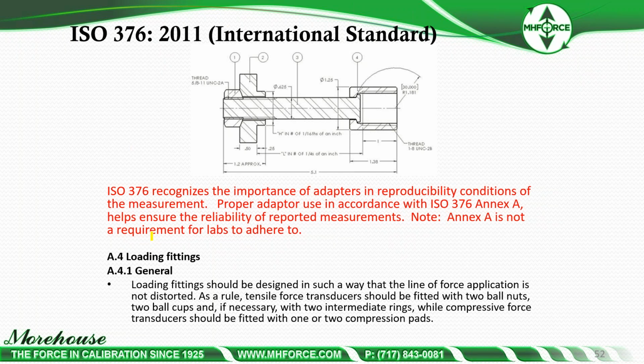And in general, Annex A 4.1, load fittings should be designed in such a way that the line of force application is not distorted. Again, keeping that line of force pure from eccentric loads. As a rule, tensile force transducers should be fitted with 2 ball nuts, 2 ball cups, and if necessary, with 2 intermediate rings, while compressive force transducers should be fitted with 1 or 2 compression pads.